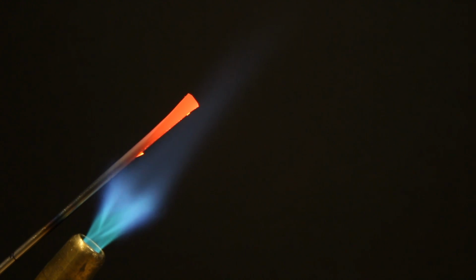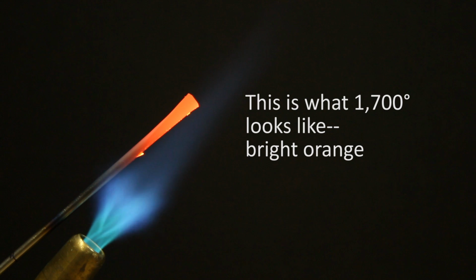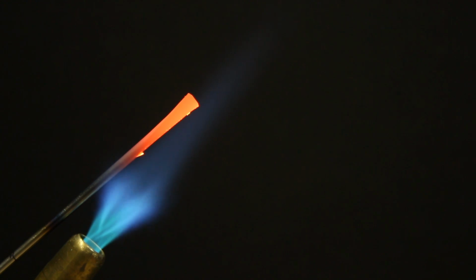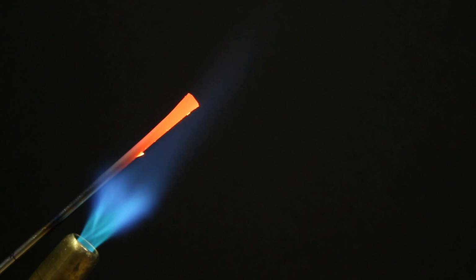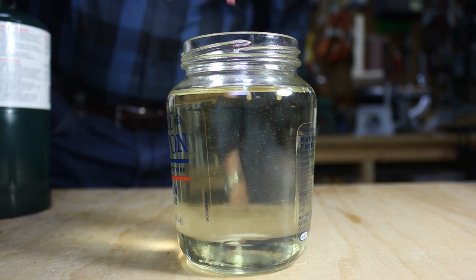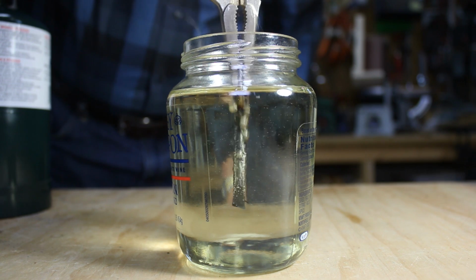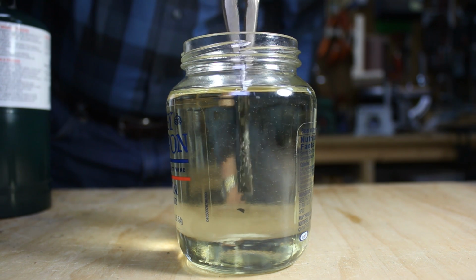How long this takes will vary based on the size of the torch flame you use. When the last inch of the blade is a bright orange color, you have reached about 1700 degrees. Don't move it just yet. Let it soak in this high heat for a few seconds while the molecular transformation proceeds. Now, plunge it down into the oil point first. It should go down vertically to minimize any warping.